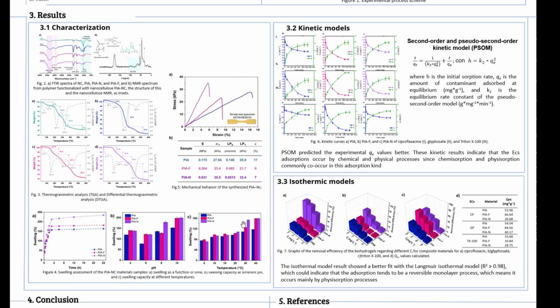The obtained biohydrogels were characterized by Fourier transform infrared spectroscopy to identify their molecular structure and determine the presence of nanocellulose, and nuclear magnetic resonance characterization was made to elucidate the chemical structure. In the infrared spectra, nanocellulose shows the oxygen-hydrogen functional group, or hydroxyl group, indicating the hydrophilic nature of cellulose fibers. Additionally, characteristic bands from polyitaconic acid are observed in the biohydrogels,